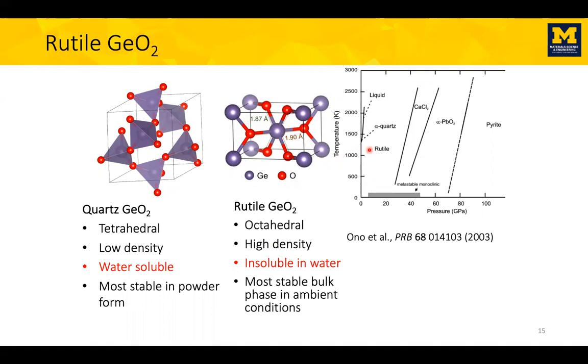If you see here the phase diagram at room temperature, the material stands in the rutile phase. And if you heat it up, there's a small window where the quartz gets stabilized before it melts. So the rutile is the most stable, and that's the one I want to focus on, because one critique we usually get is that it dissolves in water, so we're not talking about the water-soluble phase.